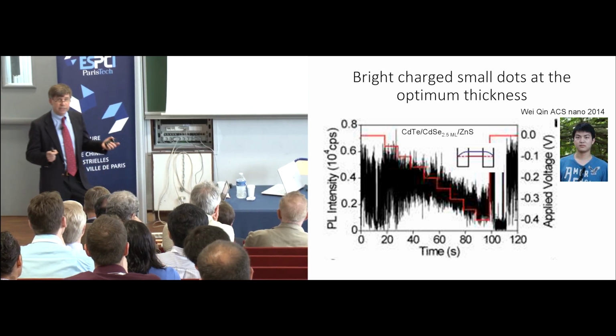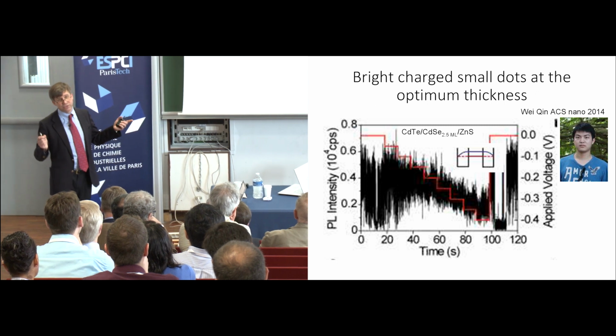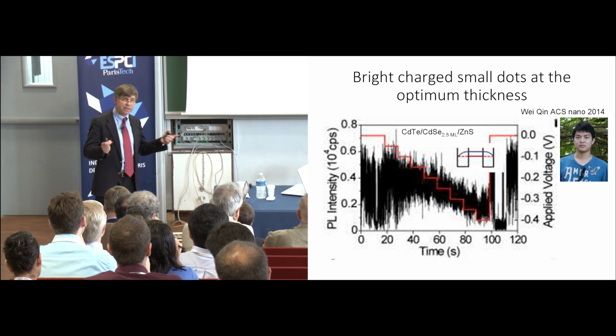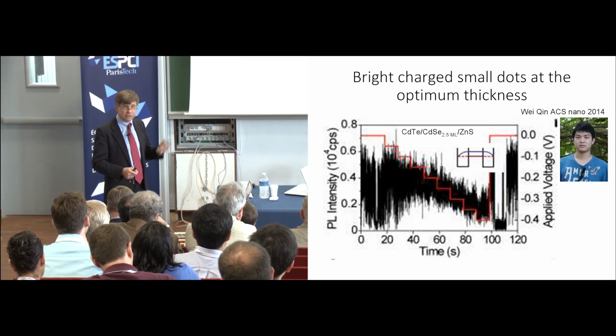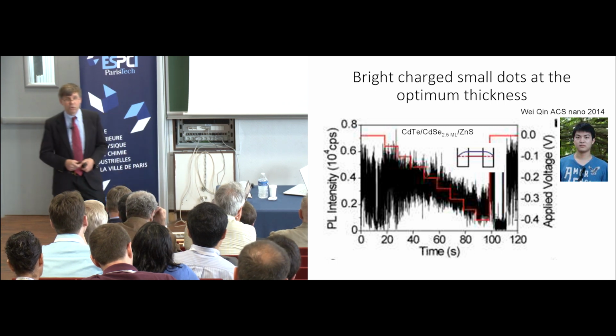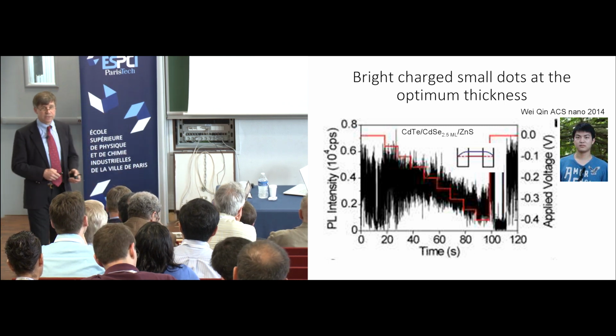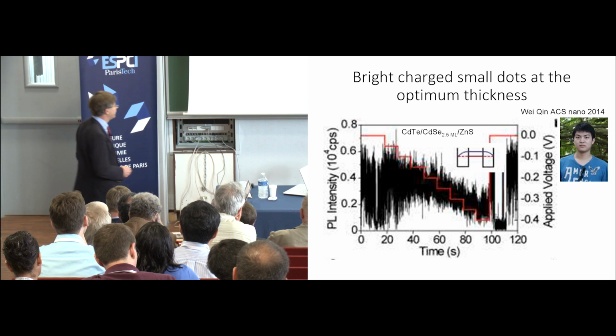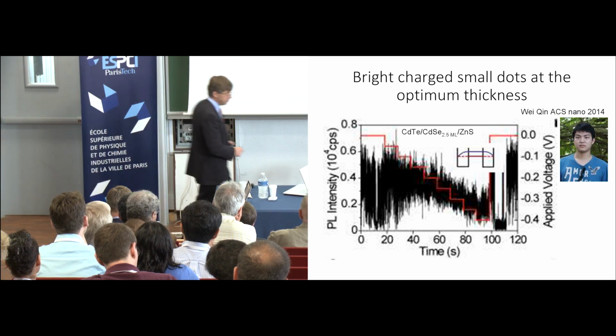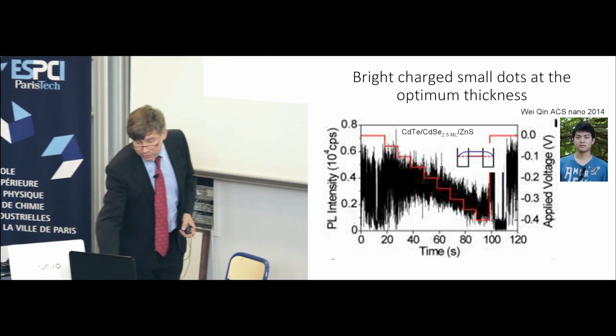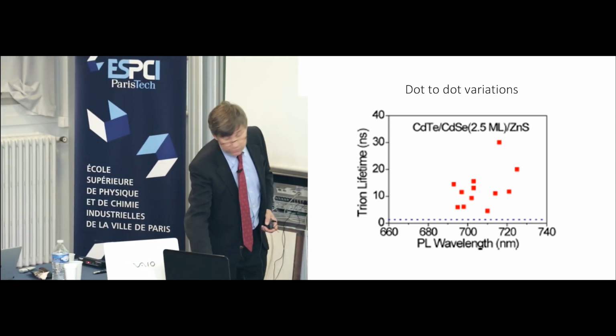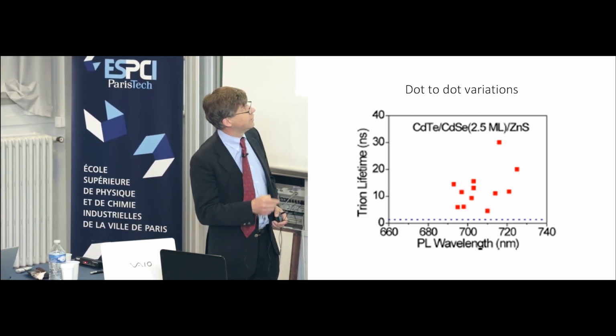And so intuitively, it seemed as if the electron has zero kinetic energy, then maybe that's why the electron-electron collision doesn't really happen with a hole. And certainly in the bulk, if the electron has zero kinetic energy, there's no Auger process. So it kind of makes sense, but it was very hand-waving. So we looked for a slightly less hand-waving explanation. This is just the variation from dot to dot. This is the champion dot.